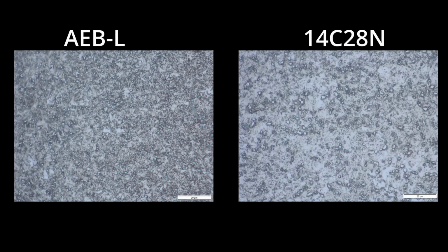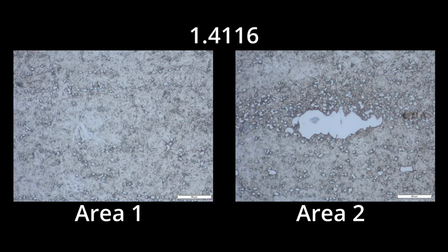Yeah, well, we know that Sandvik and Uddeholm, for example, with their razor blade steels, AEB-L, 13C26, 14C28N, their microstructures are impeccable. But you can find micrographs in the literature of X65Cr13 steels, which are generic steels of the same composition, where they will have some chunky carbides in them. So Uddeholm and Sandvik have some patents from the 70s where they really dialed in their processing, the hot rolling temperatures and the annealing process, etc., where they optimize for fine carbides, for good toughness and for high sharpness in razors and everything. So I have to think that the 4116 could be better than what I got in this particular sample. Maybe the steel company was having a bad day, or maybe they need to optimize their process more. It's hard to say.